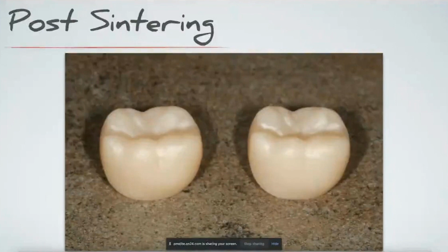post-sintering image, but compare the crown on the right to the crown on the left. If we start looking at the facial surface of that crown on the right, and we start looking at the facial surface on the crown on the left, we're going to see those striations still present. Now, are those going to be noticeable to the patient or their tongue? I don't know. But what I do know is that the one on the right took maybe 20 seconds to polish. So by using that blue Meisinger wheel and getting rid of those lines, I just end up with a nicer restoration. I like the occlusal anatomy a little bit more defined. You can see the rise and fall a little bit there that you don't see on the left. But the bigger deal to me are those striations on the facial surface.